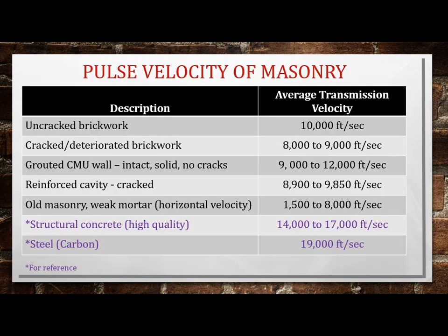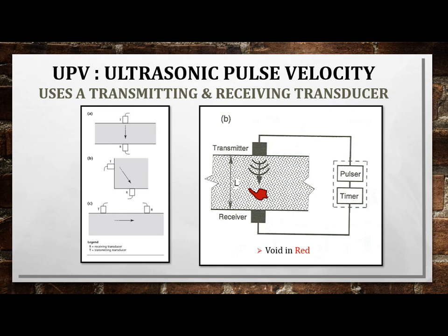Every material has an intrinsic velocity. We know the velocity of uncracked brickwork through empirical data and lots of laboratory testing and field data. We've established these velocities, so we know the velocity of good concrete, bad concrete, and the velocity of steel. So when we test, we're actually sending a sound wave, and you can learn a whole lot by sending sound waves through material. You can approximate its strength based on velocity. You can do void detection. The picture on the right shows that as the sound is traveling through a part, if there's a void, the sound has to go around the void, so it's going to take longer.